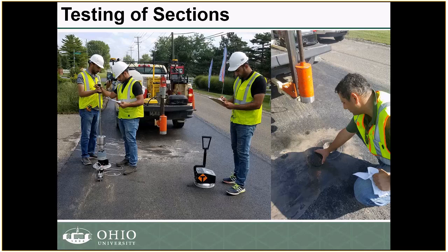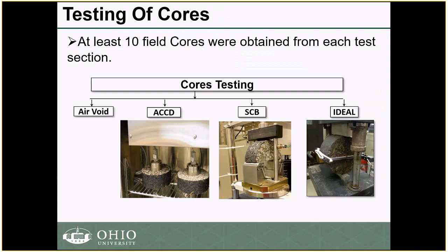Again, pictures here during coring. We did some density testing, as well as light falling weight deflectometer testing after the construction, and we also obtained at least 10 cores from each test section. We did testing on core samples as well as on samples that were prepared using the field mix and compacted in the lab.